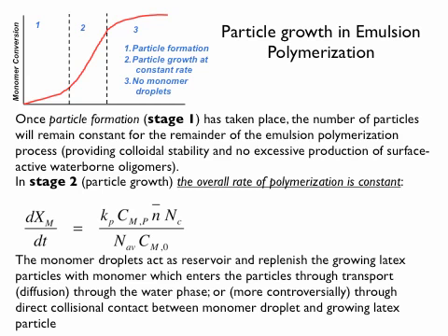The concentration of monomer in the particle is something we need to have a closer look at. The total number of particles we can figure out, because if we can measure size and we know density, we can work out how many particles there are. Then we can calculate the average number of radicals per particle, because we know how much monomer we put into the system, and the Avogadro number is known as well.